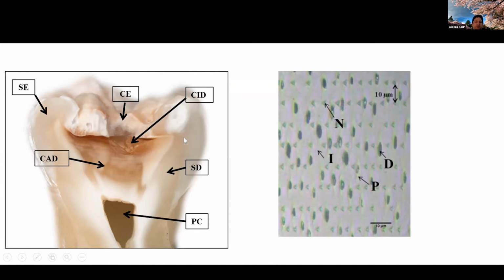So we have this very small indenter with a couple of micrometers sort of head. And we tried to distinguish the intertubular dentin from the dentinal tubules and the peritubular dentin. I know if you've read Summitt's book or any other operative book, they talk about the peritubular dentin having a higher mineral content, having lower organic content, and basically being more resistant to etching. And what the Knoop hardness shows you, and based on Fusayama's studies, is that, of course, the caries affected dentin is softer than normal dentin, but it has some relative hardness, right? That can be a good guide for removal of caries.